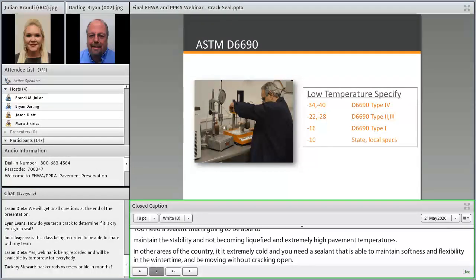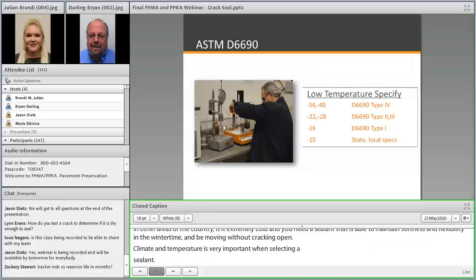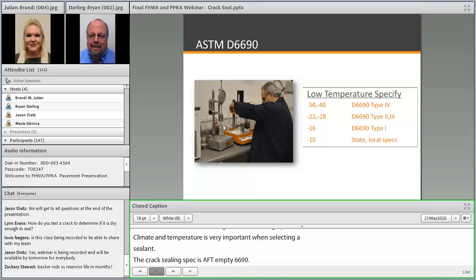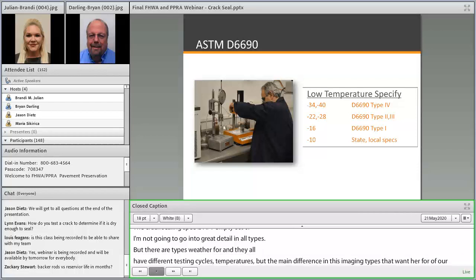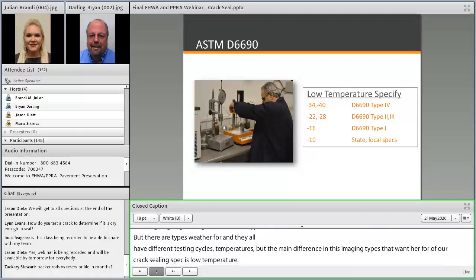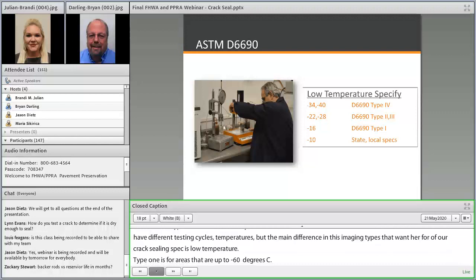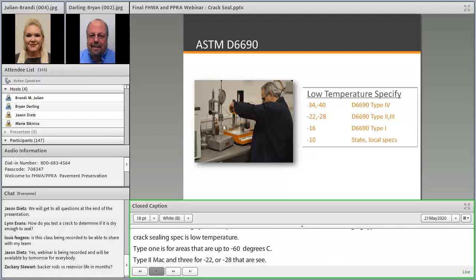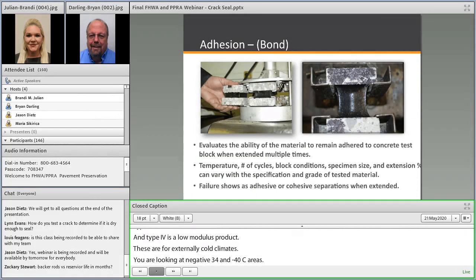And the crack sealing spec is ASTM D6690. I'm not going to go into great detail on all four of the types, but there's type 1, 2, 3, and 4. And they all have different testing, cycles, and temperatures, but the main difference distinguishing type 1, 2, 3, and 4 of our crack sealing specs is low temperature. Type 1 is for areas that go down to negative 16 degrees C. Types 2 and 3 are for negative 22 or minus 28 C. And type 4 is what we call a low modulus product. These are for extremely cold climates, so you're looking at minus 34, minus 40 C areas. So that's the main differential between the four types of the crack sealing spec, is that low temperature.